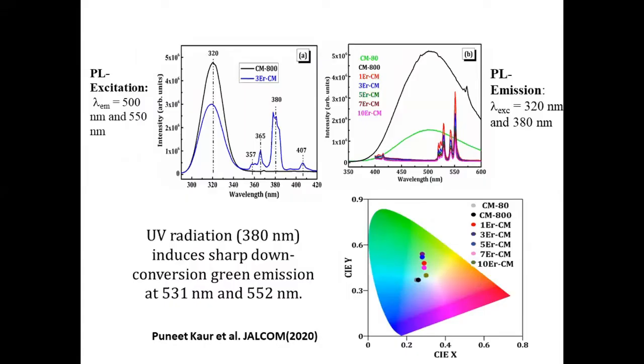And we study the luminescence. Here again we see strong concentration quenching effects. As you increase the erbium oxide concentration from 1 to about 3 mole%, the luminescence intensity falls. So we see green light emission when you excite it with 320 nanometer and 380 nanometer. These lie in the UV region. So erbium doped samples, they are good green light emitters. So it is showing down conversion. We are converting UV light to visible light.